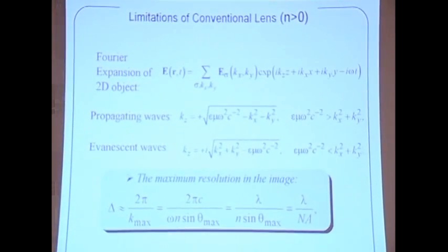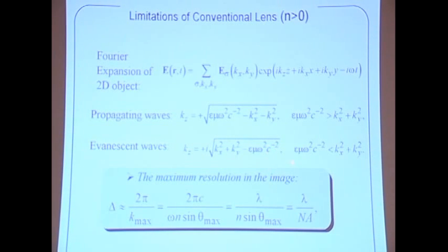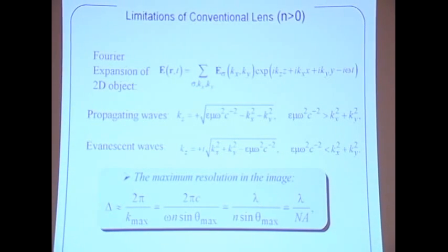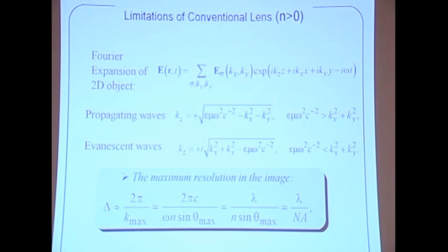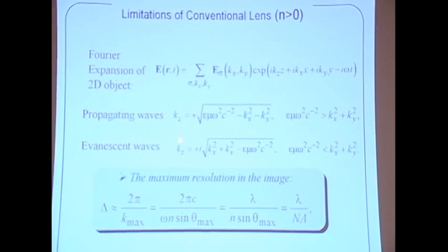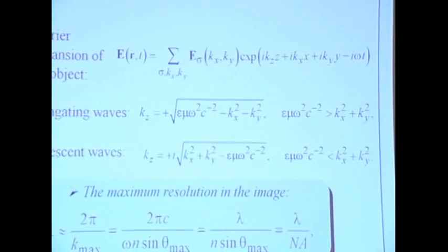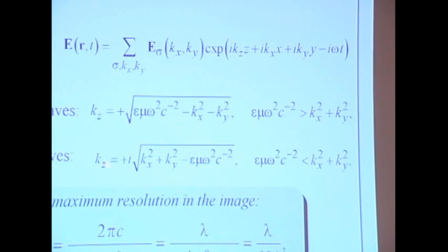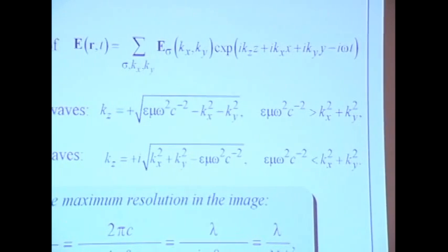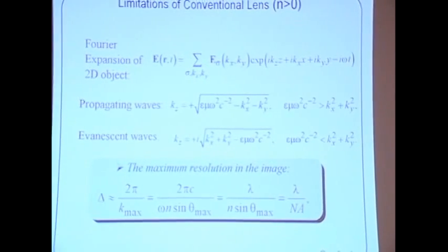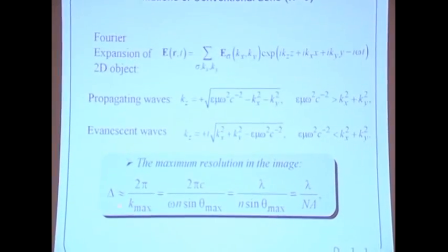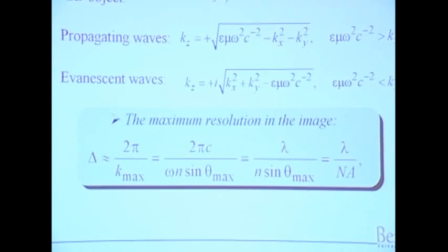So this imaging is essentially a Fourier transform process. However, if the kx, ky are large, for example, there are some very nanoscopic features on my face you want to image, that corresponds to a very large k vector. That forces kz to become imaginary because kx, ky, kz squared has to equal omega over c squared. So if this is larger than omega over c, that gives you kz imaginary. That corresponds to the so-called evanescent wave, which is not propagating, it is a decaying field. So for most imaging, what you collect is a propagating wave. And that is imperfect, so you lose some large k-vector Fourier components. And that gives you the so-called diffraction limit, where the diffraction limit is the largest k you can collect. It depends on the